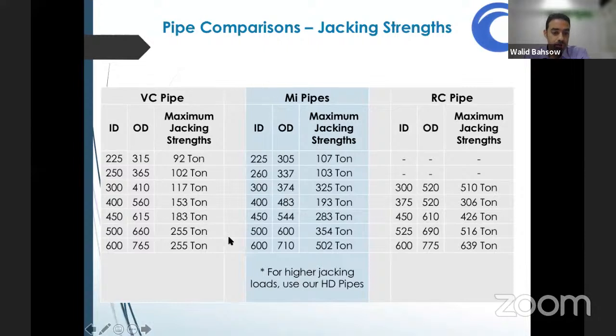For the jacking strength, we can see the information available for our standard duty pipes. We have two ranges of pipes, standard duty and heavy duty. I'm trying to compare with the minimum available. For the same diameters, for example, we have a 260 internal, here it's 250. The external diameter is much less, and the jacking strength is almost the same. And for the remaining sizes, the jacking strength increases and goes higher.